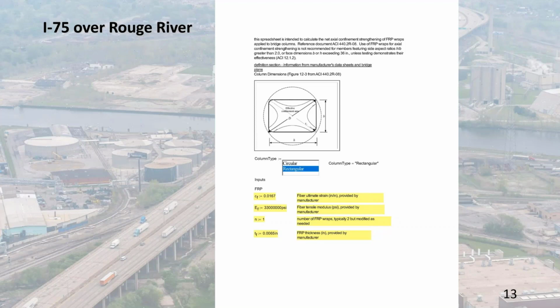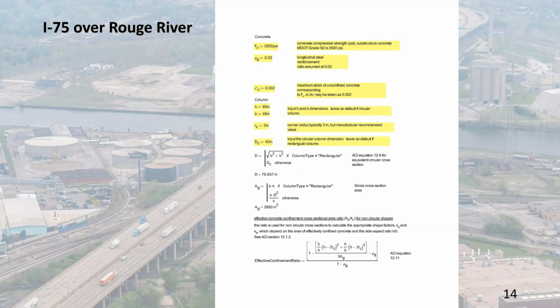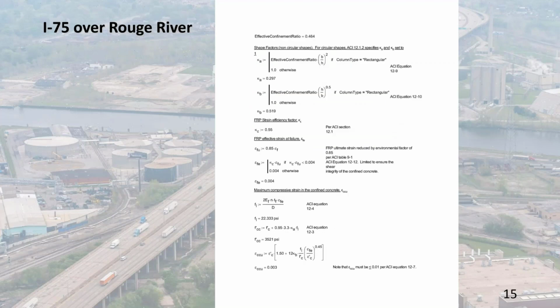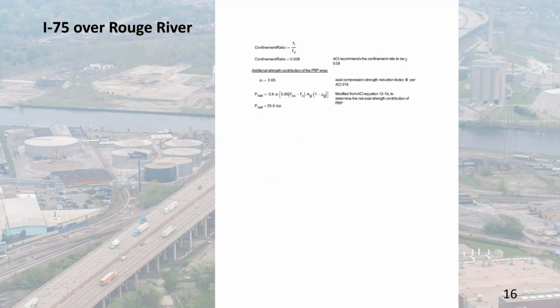And as you can see from the sheet here, we do have rectangular columns. So we selected those appropriately and started entering in strain values and the tensile modulus. We go through the inputs for the concrete and the strains in the concrete. And again, we calculate the equivalent circular cross-sectional area for the column, and we calculate the effective confinement ratio per ACI. We go through all of the applicable shape factors, the FRP strain efficiency factors, the strain at failure, and then we can calculate the maximum compressive strain in the confined concrete. And from there, we get the actual additional capacity provided by the FRP system to the benefit of the column.